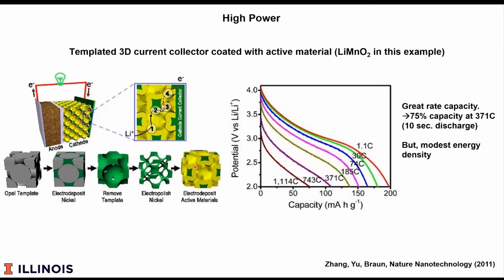We also determined how to put the active material shown in yellow on this. And because this contained a very effective transport pathway for the electrons, the metal in green, and a rather effective pathway for the ions, in this case it was a face-centered cubic structure, so while the tortuosity was not 1, it certainly was not order 5 or 6. And so there was a fast pathway for lithium ions and a fast pathway for electrons. And what we saw is that we could discharge 75% of the capacity in 10 seconds.